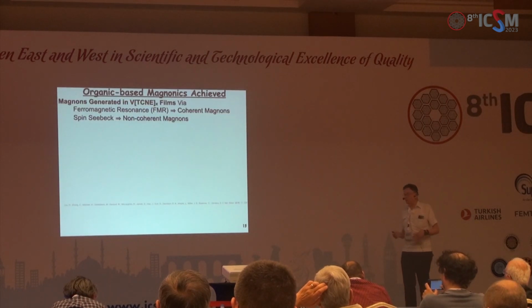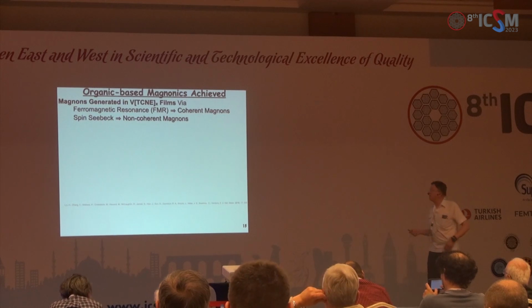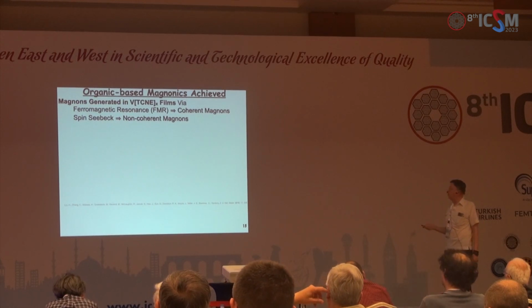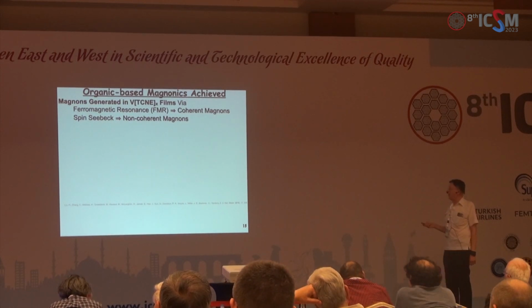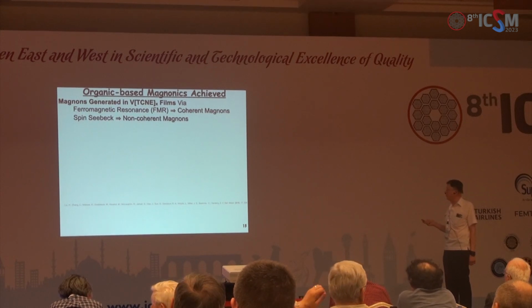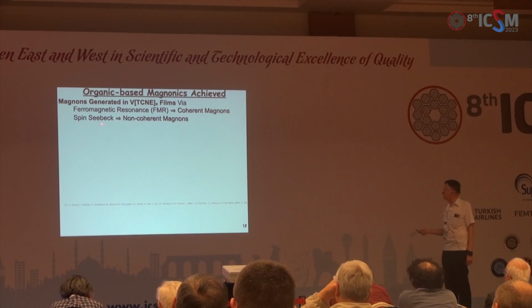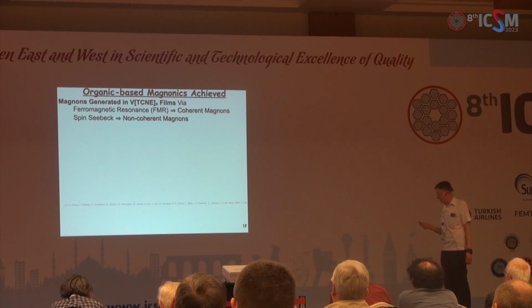The bottom line, which is a whole talk unto itself, is that we can generate magnons by ferromagnetic resonance to get coherent magnons and use a spin-Seebeck effect to get non-coherent magnons.